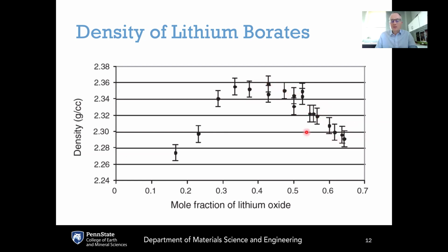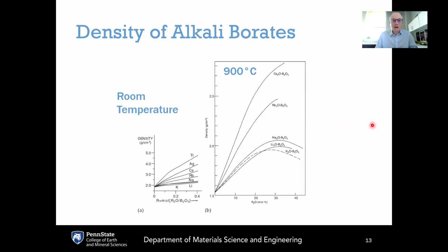So this is just another manifestation of the boron anomaly because of the two different structural roles that modifiers play in borate glasses. In this initial regime, converting boron from threefold to fourfold coordination, and then in this higher modifier regime where non-bridging oxygens are created.